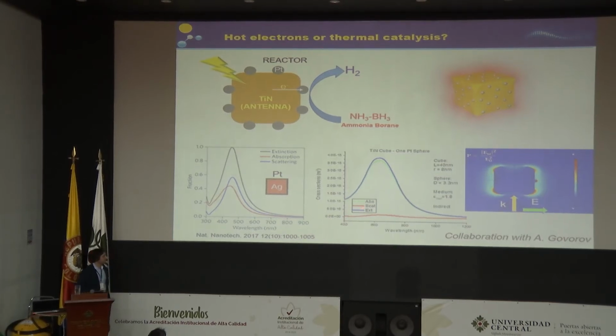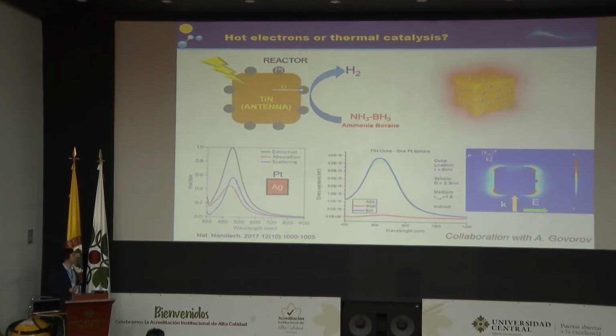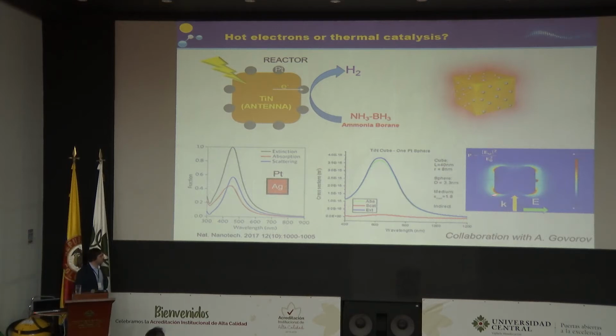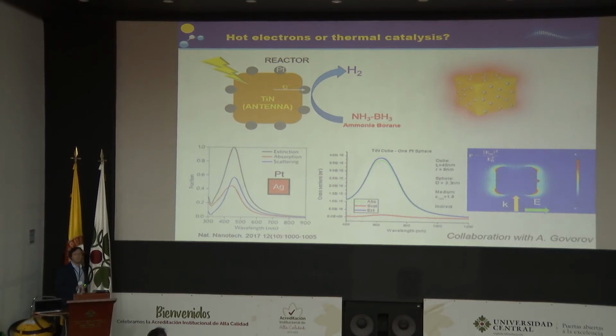Otherwise, for titanium nitride, we have a really low amount of scattered light, and most of the light is absorbed inside the material. This means that we can create a large amount of hot electrons or heat by using these hybrids. And here it is again more clear. We can see the resonant excitation of the surface plasmon in titanium nitride cubes, where we just put one particle of platinum. Of course we have hot spots of the surface plasmon at the vertices of the titanium nitride, but this plasmon also decays on the surface of our catalytic material, which is what we want for this kind of reaction.